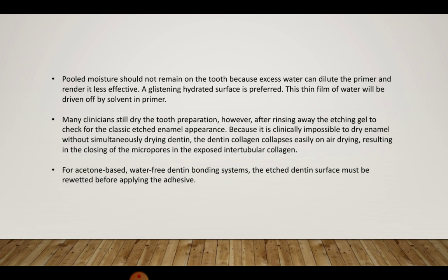Pooled moisture should not remain on the tooth. The dentine should be slightly moist but not too moist, because if there is pooled moisture, there will be excess water which will dilute the primer and can render it less effective. So, the ideal requirement is a glistening hydrated dentinal surface. A thin film of water should be there which will be driven off by the solvent and primer.